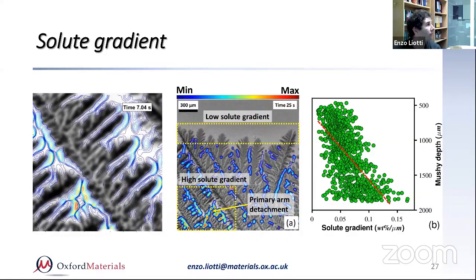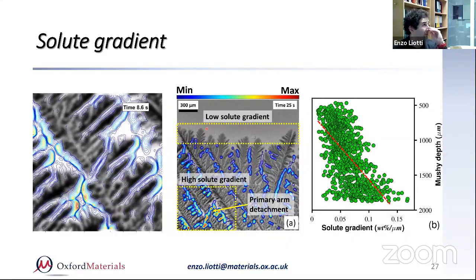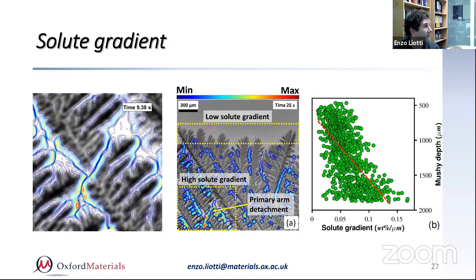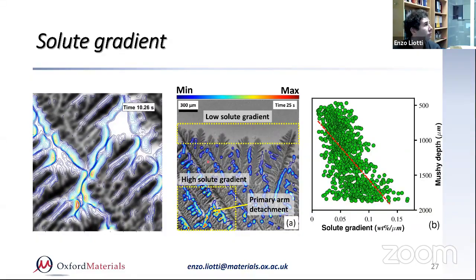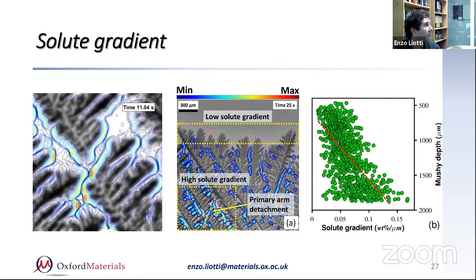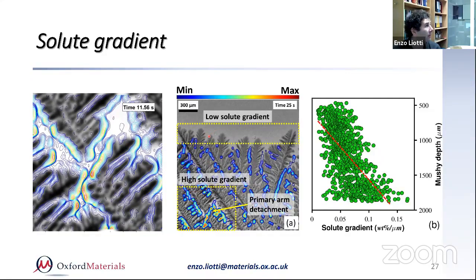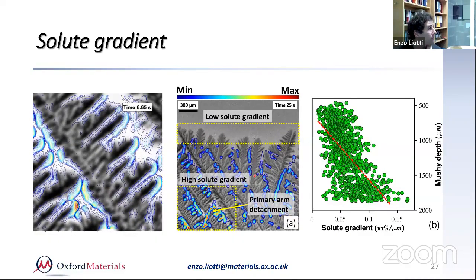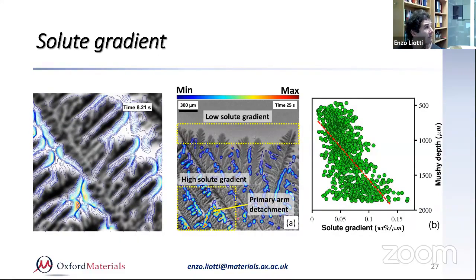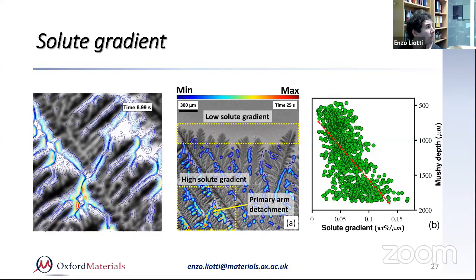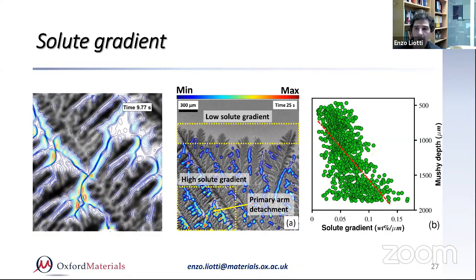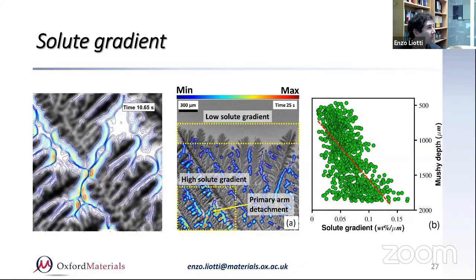Also, we started to look inside the mushy zone at how the distribution of the solute gradient is. If the mushy zone is like this, the one in the image in the center, the solid fraction is 0 at the top and then will increase going down, right? And we measured the solute gradient. By looking at the images in the liquid and measuring the concentration of the liquid within the interdendritic channel, we were able to measure the solute gradient as expected. The solid fraction increases, but also this horizontal gradient, which is represented by this color map, increases while you go deeper in the mushy zone, as shown here.